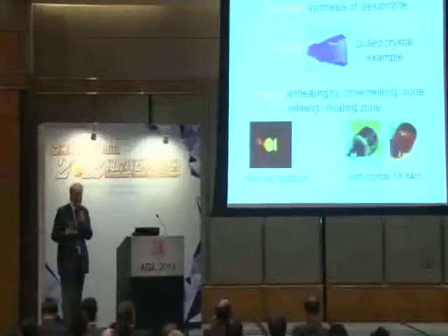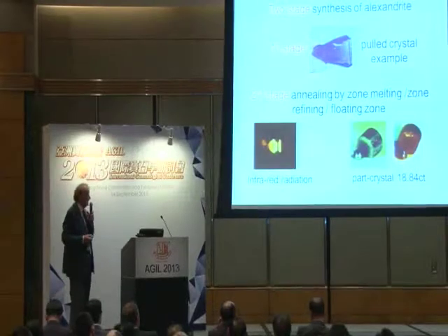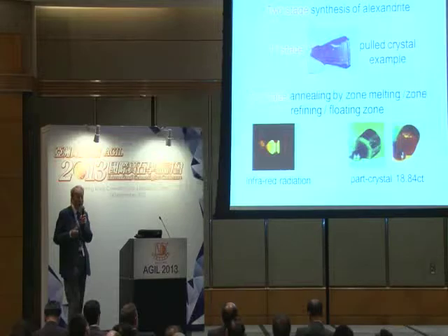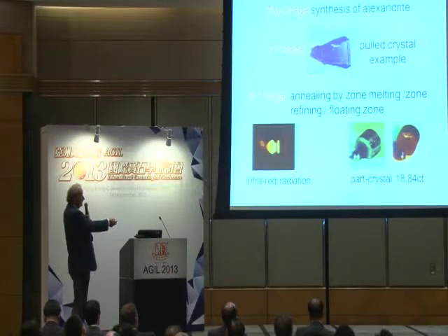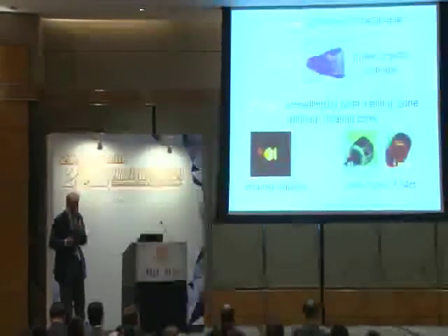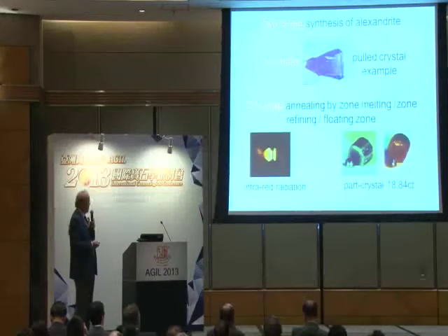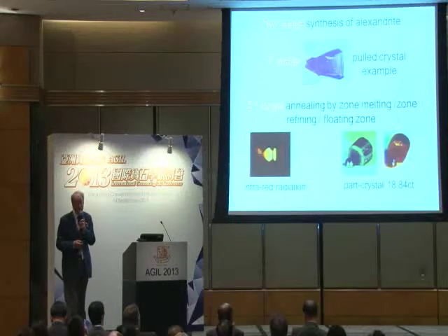in diameter. Now in that process, because titanium was used in the growth of the synthetic, the titanium grouped together to become rutile, and we then got the cat's eye. And I remember when I gave this rod to my cutting friend and said, "Oh, will you cut me a cabochon?" And I looked forward to getting the cat's eye, and sure enough, I got a cat's eye alexandrite back. But there was only half the crystal used, and I said, "Well, cut me another one, but cut it at right angles to the first one, just for fun, really."